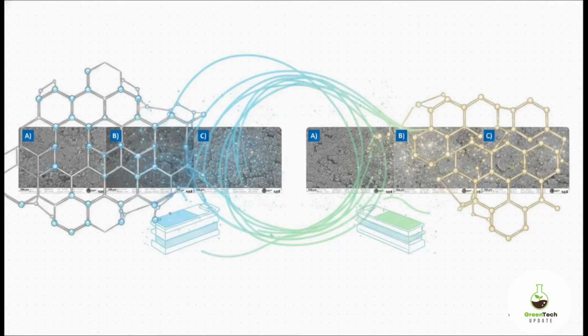And when we look under the microscope, we can actually see the physical results of this synthesis. On the left, we've got the zinc integration, and on the right, the calcium. Just look at how incredibly smooth and continuous those surfaces are. There are no visible salt precipitates, no weird phase separations. The metallic salts have integrated perfectly and seamlessly right into that nitrogen-rich polymer matrix.